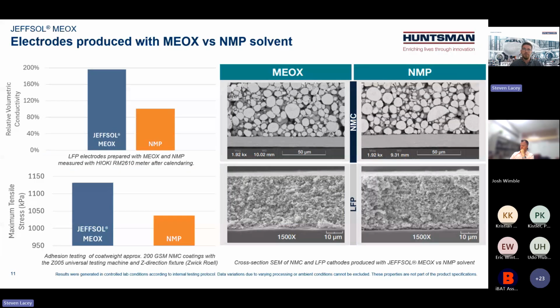Now, once you cast it onto aluminum foil in this case and dry the electrode, we just wanted to ensure from a third-party validation that we still have a very homogeneous electrode throughout the entire cross-section. So we have cross-section SEM comparisons between MEOX and NMP in both NMC and LFP cathodes here. And as you can see, the distribution of all the components is very similar. There's no real difference here. Maybe if you look very closely at the LFP on the bottom right, you might be able to see a bit of a gap between the aluminum foil and the LFP cathode, which could result in the lower conductivity and also the lower adhesive strength of the NMP system versus MEOX.